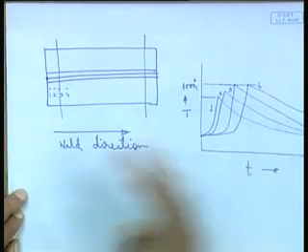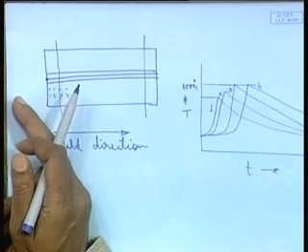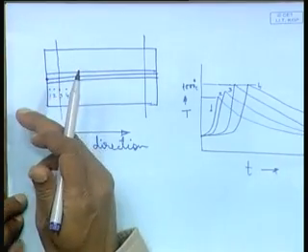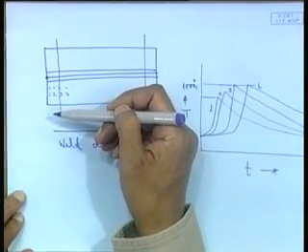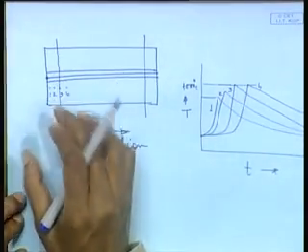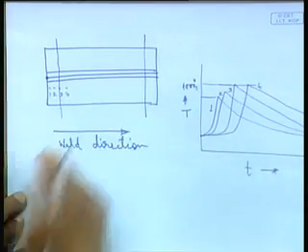Why is that happening? Because the plate here, the plate was not there. So the heat flow pattern was different. Heat could not flow in this direction because there is no conduction, no plate is there, but there was convection from the plate edge. Whatever heat loss has taken place through convection, here it is, that means the conduction, convection, the overall heat flow pattern stabilized after the location of point 3. After the location of point 3, that is the better way of putting it. That means the heat flow conditions stabilize beyond a certain point. Again, it becomes unstable while nearing the end.